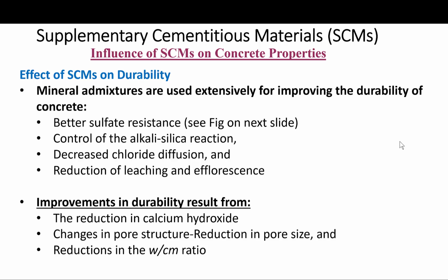Firstly, they reduce the permeability of the concrete and inhibit the ingress of soluble sulfates. Secondly, they reduce the amount of calcium hydroxide, which is taken from the system. By this, they limit the formation of gypsum from soluble sulfates, because soluble sulfates react with calcium hydroxide to form gypsum, which participates in ettringite formation.